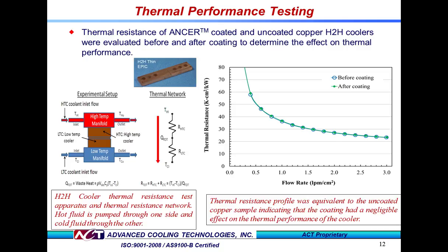The overall thermal resistance network is seen next to the experimental setup. The samples were tested before and after the ANCER coating was applied. As you see on the plot on the right, the lines before and after coating are on top of each other. From this we conclude that the ANCER coating does not impede or degrade the thermal performance of the microchannel cooler. So we have shown that the ANCER coating provides significantly lower corrosion rate, but does not affect the thermal performance of the copper microchannel cooler. Let's next look at whether the coating affects flow performance.